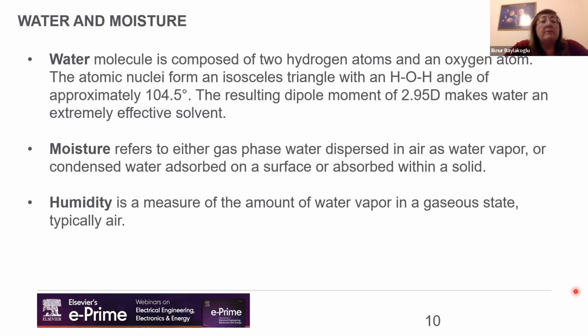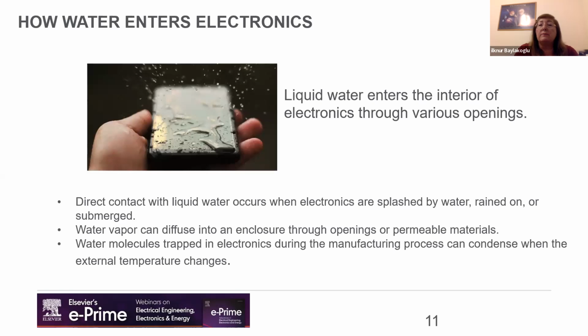When we have contracts for high technology products, they usually ask for parameters for humidity and temperature. They expect our product to be able to work under these types of conditions. We define absolute humidity as the total mass of water vapor present per unit volume of air, and relative humidity as the ratio of the partial pressure of water vapor to its saturated or equilibrium vapor pressure, which refers to the moisture capacity in the air. So relative humidity depends on temperature and pressure. For a fixed absolute humidity, when the ambient temperature falls, the saturated vapor pressure decreases and the relative humidity increases.